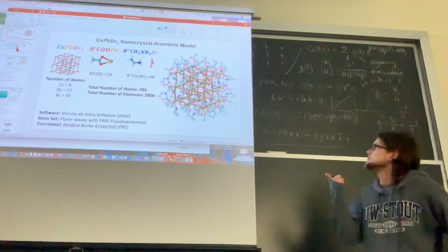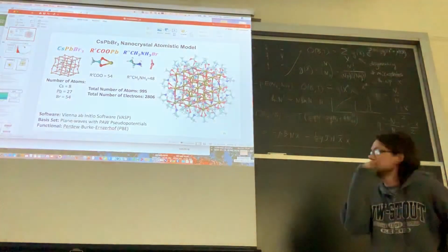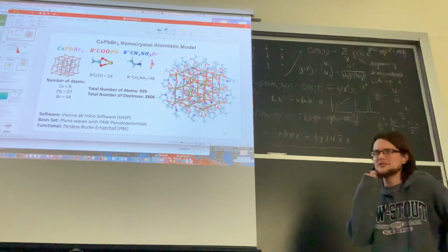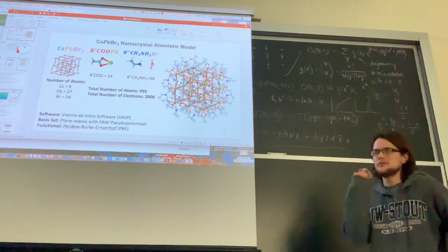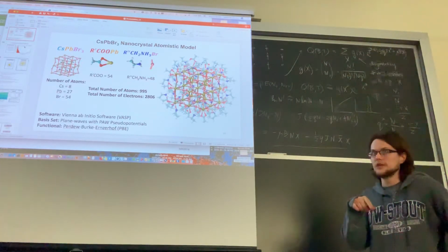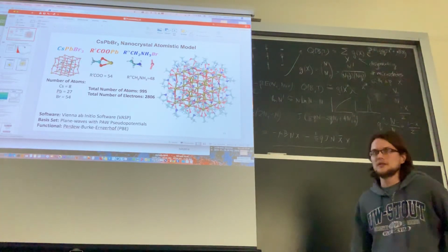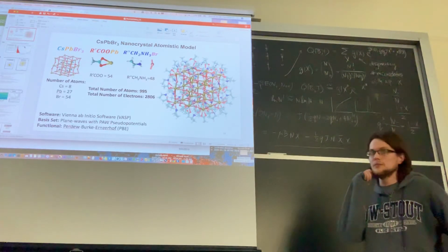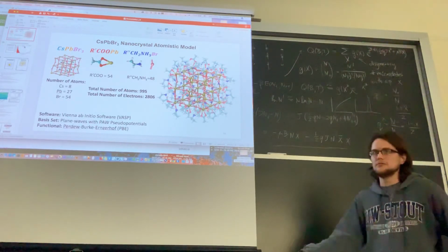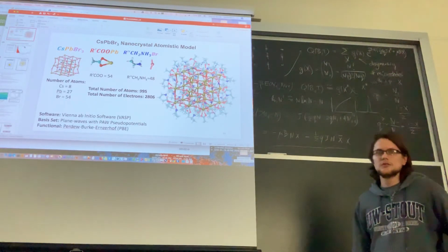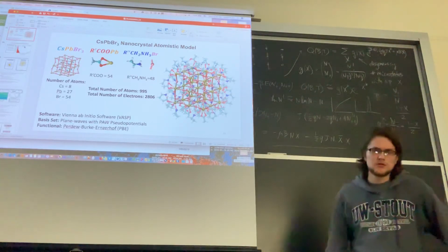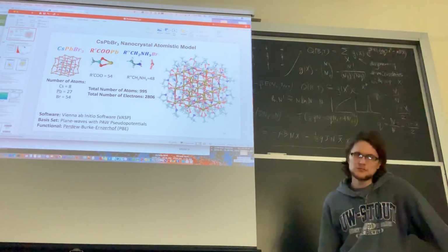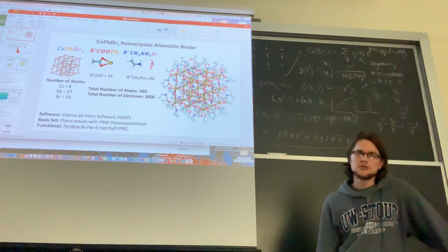But then these nanocrystals were initially made in 2015. That was the first time they were synthesized, and that's where they realized the wide color gamut, or high color purity, they have. And so that's where the LED idea came from: make films of nanocrystals instead of bulk film. It comes from careful capping of surface sites with carefully chosen ligands.